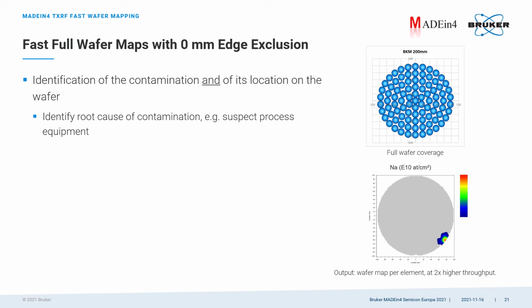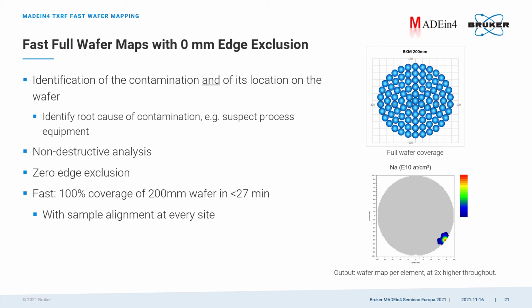A full wafer map on a 200mm wafer with wafer alignments on every side used to take almost 1 hour to measure in the beginning of this project. Now we can measure this about 2 times faster, still aligning the wafer at every site. So these are altogether very nice productivity improvements obtained in Made4.